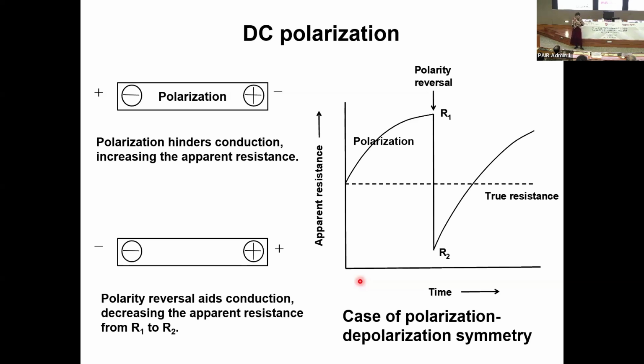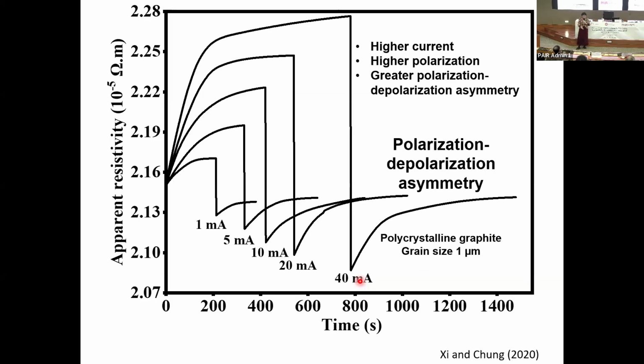Okay, I already explained this DC polarization, and this schematic picture here shows what I call polarization, depolarization symmetry. You see this R1, R2 is symmetrical, okay? But in reality, for materials, very often it's not symmetrical. That is shown here. You see the curves get more and more asymmetric as the DC current increases. Also, the highest point, that plateau, becomes higher and higher, meaning more polarization as you have higher current. Okay. So this is polarization, depolarization asymmetry, which is natural there.